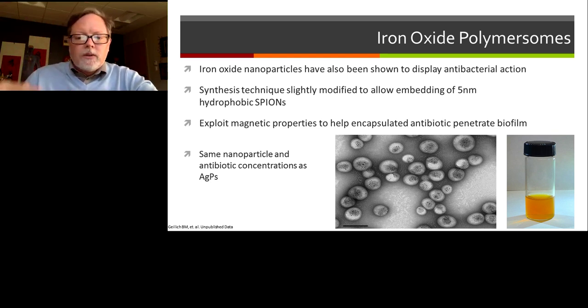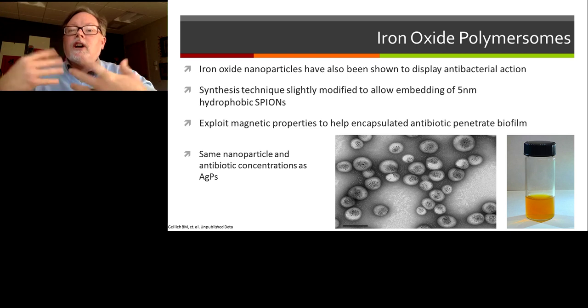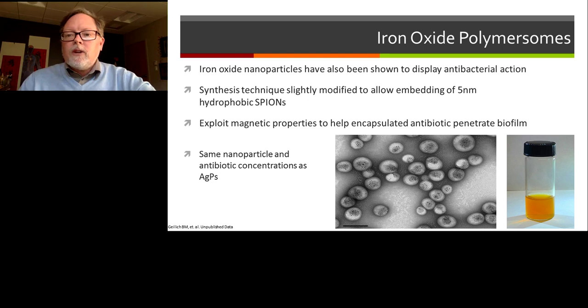So if you have an infection in a remote, hard to get to location in your small intestine, you could inject a patient with these iron oxide nanoparticles, use a magnetic force to drive those particles to that infection, determine if you have an infection, because again, you can image these iron oxide nanoparticles, and then in real time, you can watch. Is that infection reducing? Is your treatment ineffective, and you need another injection of iron oxide nanoparticles? You can watch the treatment occur while you're in the hospital or in that doctor's suite.